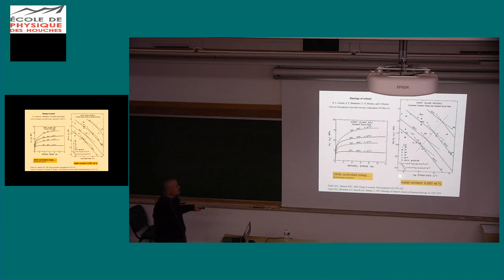And this salt, the Avery Island salt, which is a very nice homogeneous kind of salt, has a water content of 0.01 weight percent. But there is water in it, and they have already recorded it. You can measure this water content using infrared techniques. And please keep this in mind, because it will come back as a very, very important thing.